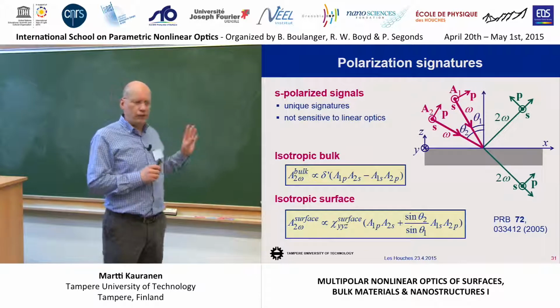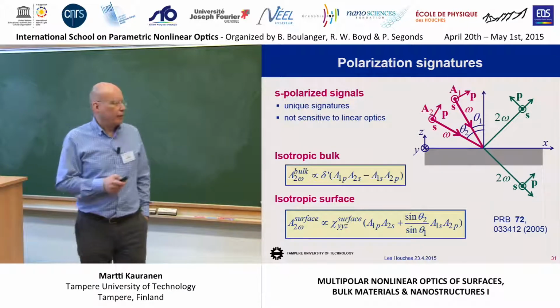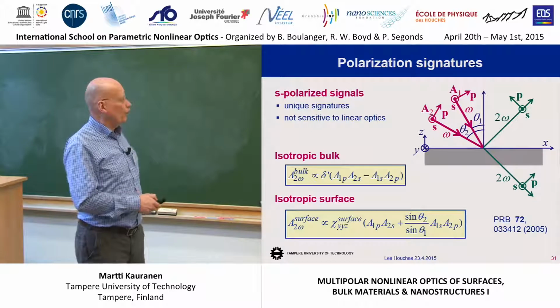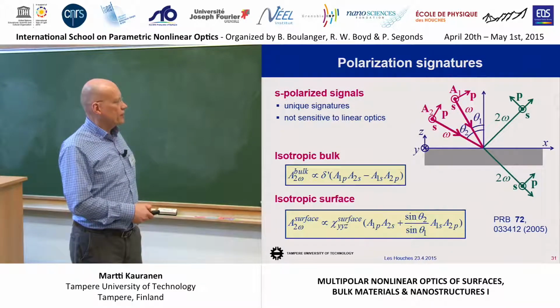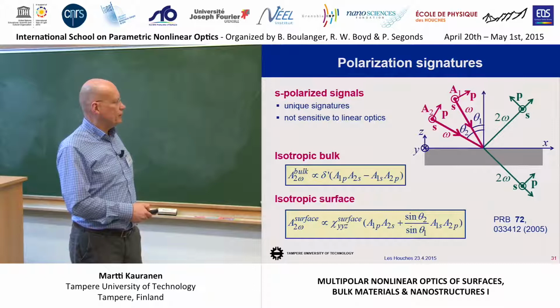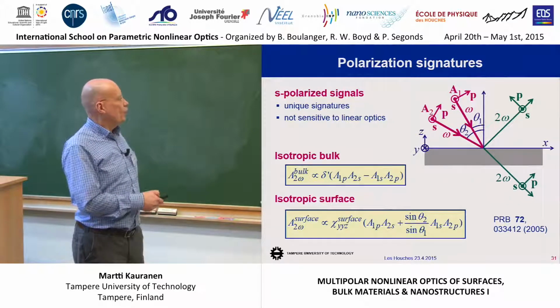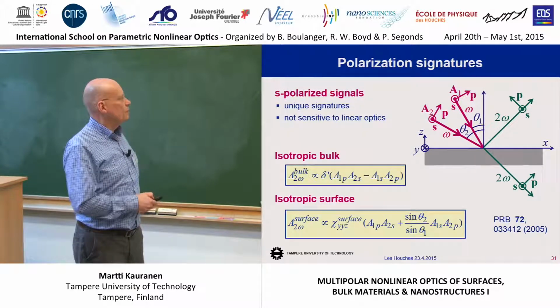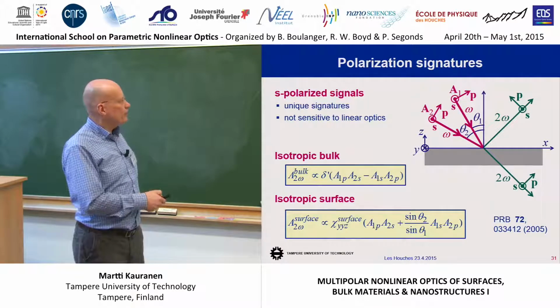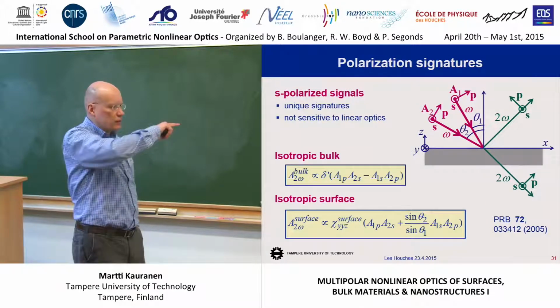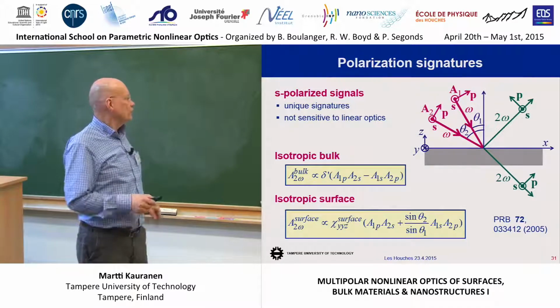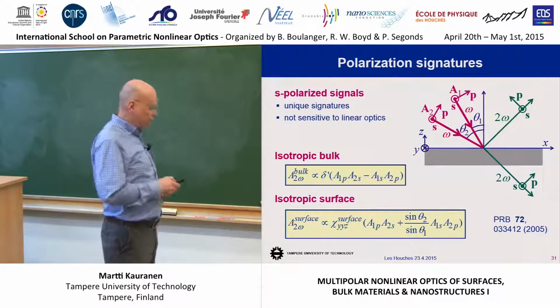In general, we like to do polarization measurements. By that, what I mean is that we detect certain polarization components of the second harmonic signal, and then we modulate the states of polarization of the 2 fundamental beams. Oftentimes, as you're going to see, we want to fix the polarization of one beam, for example this one, and then use a wave plate to rotate or modify the state of polarization of the other beam. So we make polarization scans, and then we can fit those into certain models and so on.